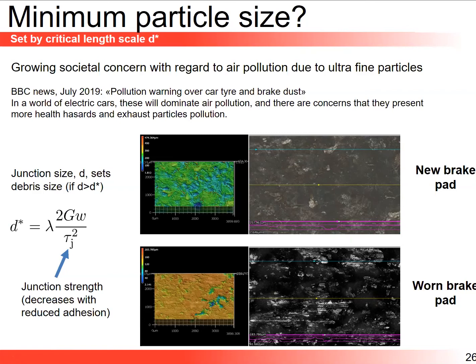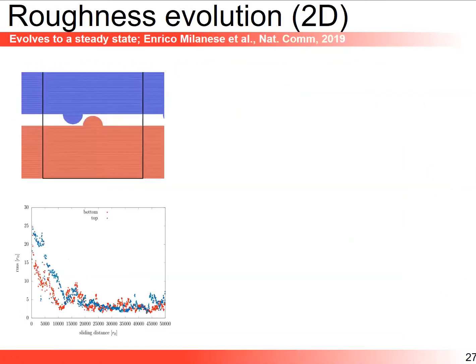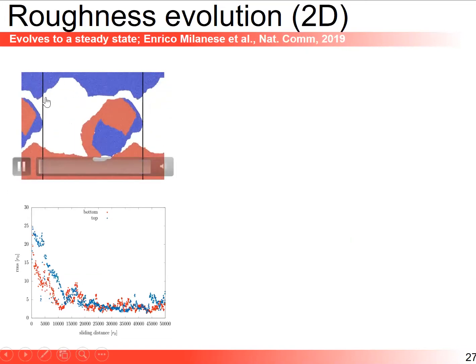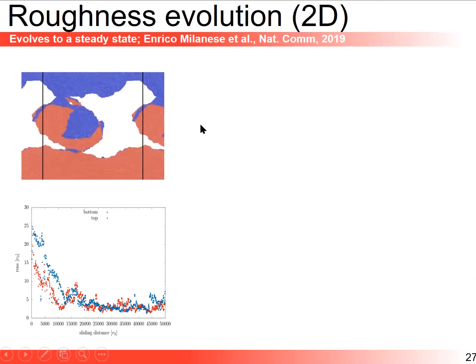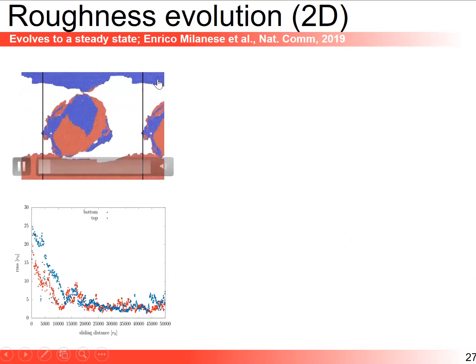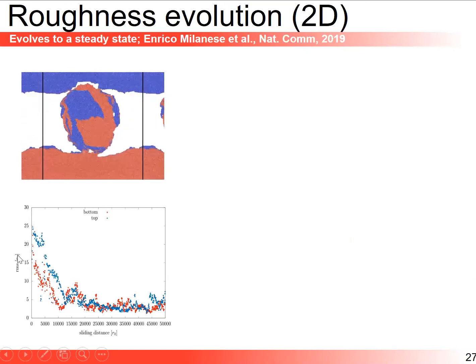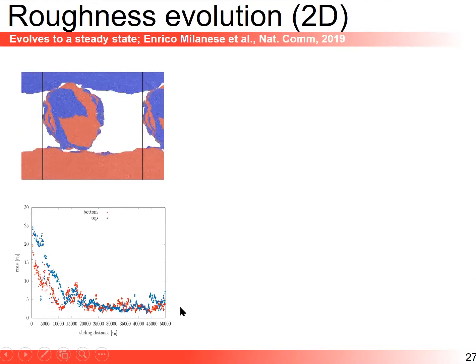Okay, what we have done was a homogeneous material, a perfect material, but now here we have defects, we have inclusions, and that I think still remains an open question. Also, what's intriguing to us, and just one slide to summarize this more recent paper from a student in my lab, Enrico, is, and it's still a mystery to us, but I told you that when we form debris, we observe that over a long time scale, we develop roughness. And we've extracted this roughness for the bottom surface and also for the top surface. And we see how the RMS, root mean square, evolves with time. We reach a steady state eventually.